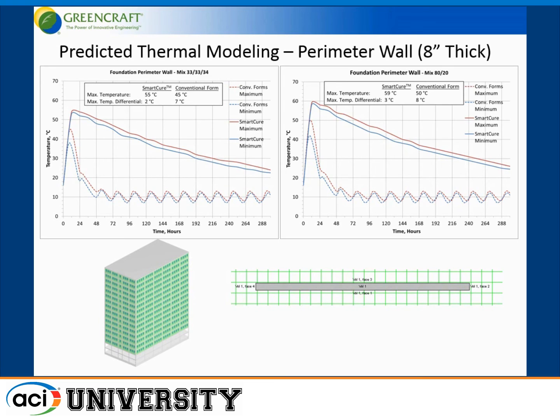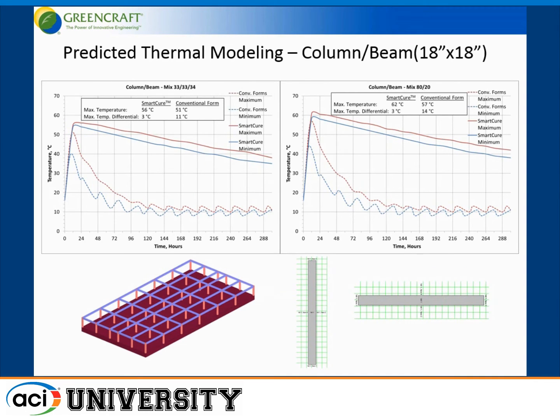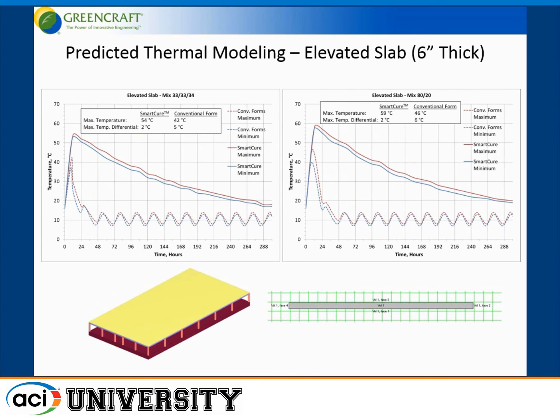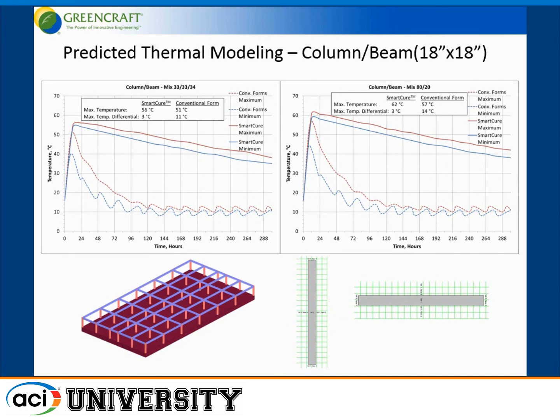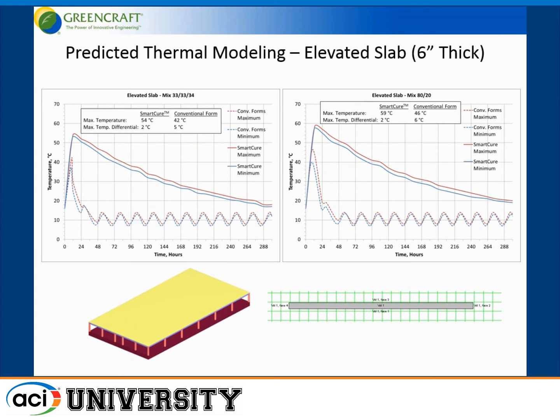So I'm going to go a little bit quicker through these slides. Basically, they show the thermal modeling, which is consistent with the real life measurements that we've done in the Atlanta project. And the thing, no matter what element we model, whether we have these 18 by 18 columns and beams, or you have the slab or the walls, is the same result. Less temperature differential between the surface and the core. The self-annealed concrete has a more sustained reaction and then a slower cooling off, while in the conventionally formed concrete, you're still riding the bull.